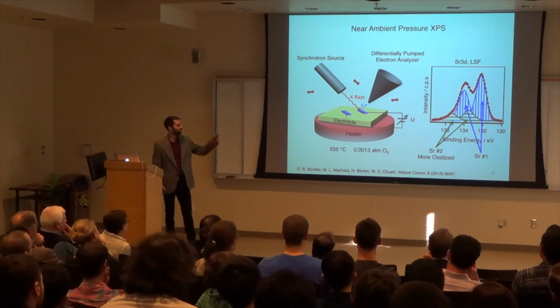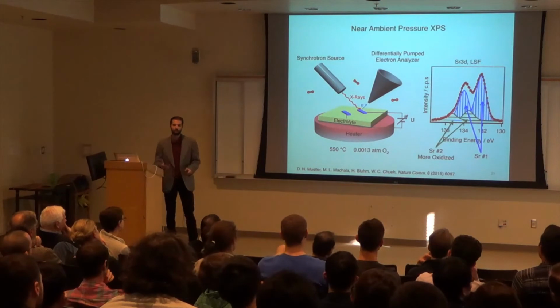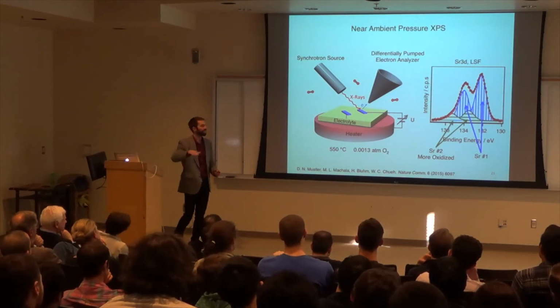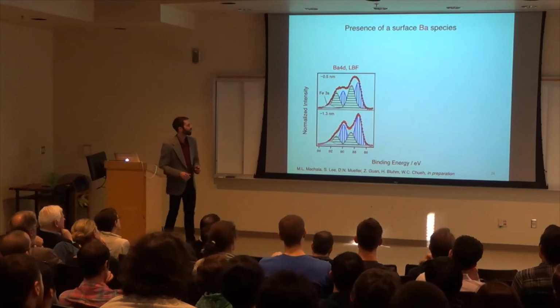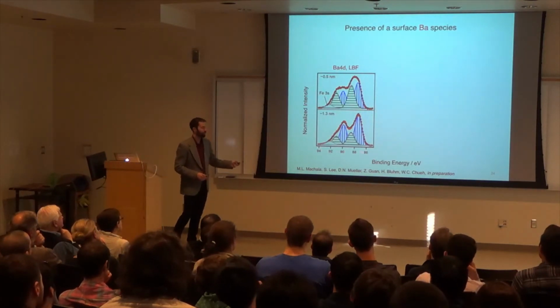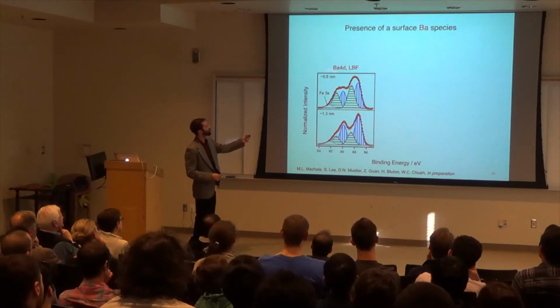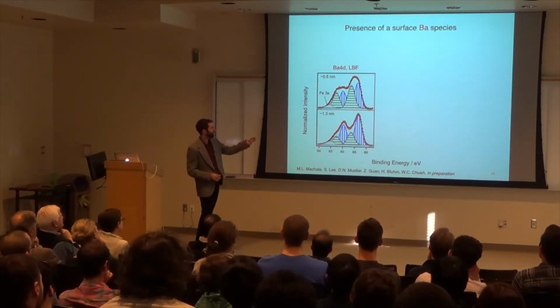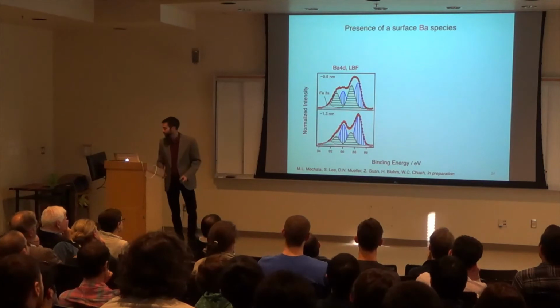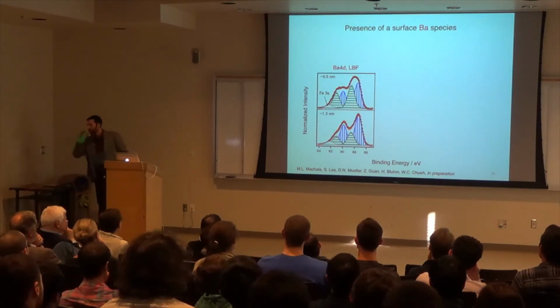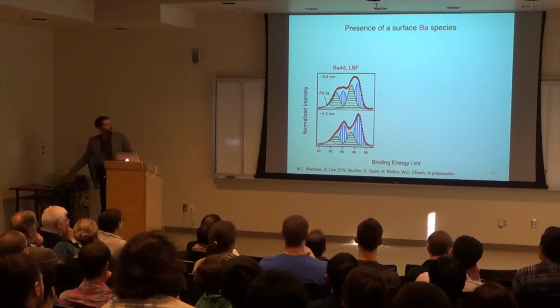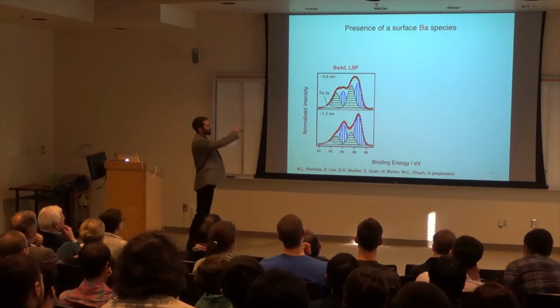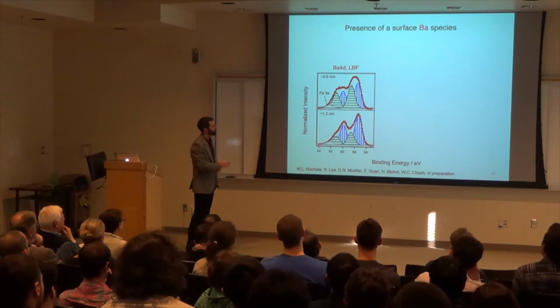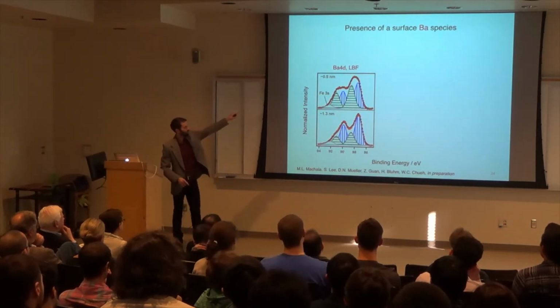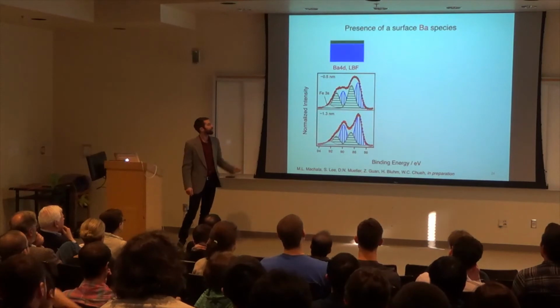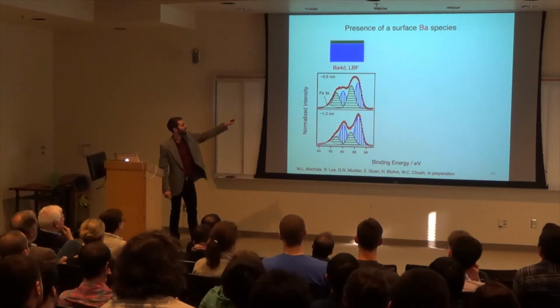Okay? So to figure out physically where these elements are, we have to do depth profiling. Something that's more surface sensitive, something that's a little bit more bulk. And so that's what I've shown here. Again, we have the intensity on the y-axis as a function of binding energy. And on top, I have a more surface sensitive measurement compared to that below, 0.5 nanometers versus 1.3 nanometers. And if you look at the relative ratio of these two peaks, the green and the blue, you can see that the ratio changes as you go from more surface sensitive to more bulk. And this basically tells us that the peak on the left is more found at the surface.